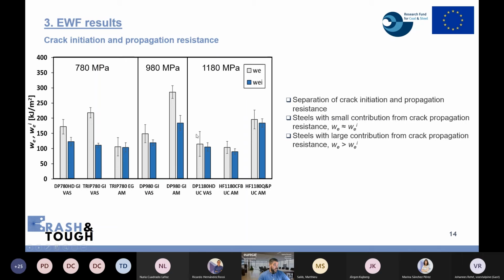But we can see in others, like the DP980 AM or the TRIP 780 from voestalpine, that this contribution after the crack initiation, this energetic contribution to crack propagation resistance, is very high. So a single parameter for crack initiation is not sufficient to define the overall fracture performance.